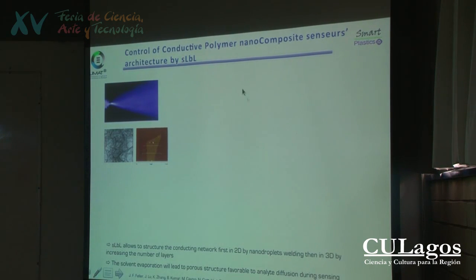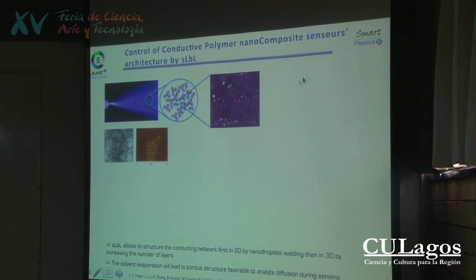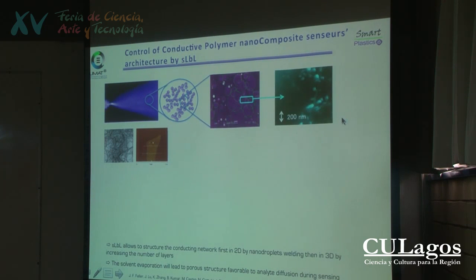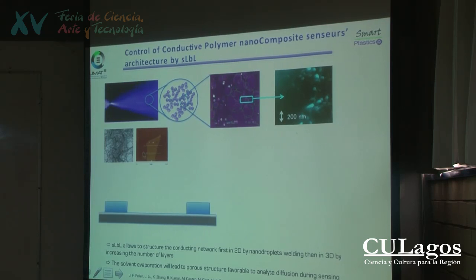So we have developed a special process to design these sensors based on spray. So spray is like paint, for example. And the interest of this spray is that you can control the structure at the different scales of the observation. Like for the gecko foot, you have the scale of the droplets, which is about 50 microns. And in these droplets, you have another scale, nanofillers, nanotubes, or nanoplatelets, like graphene.